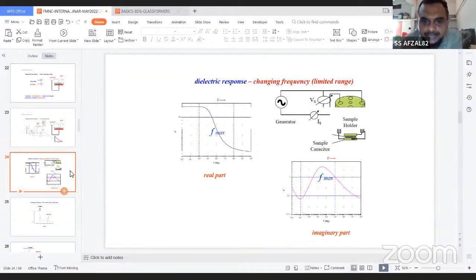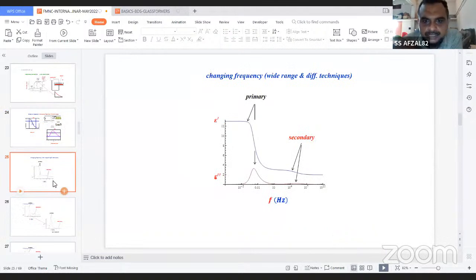melting temperature, that is minus 150 degrees Celsius to melting temperature, because that will be in the glassy state. So first of all, we have to melt the sample to become a liquid, and then quench cool the liquid to become a glass. And then in the glassy state, at different temperatures, we will measure the molecular dynamics, and in the supercooled liquid state also we will measure the molecular dynamics, and from that data we will understand the stability of this.